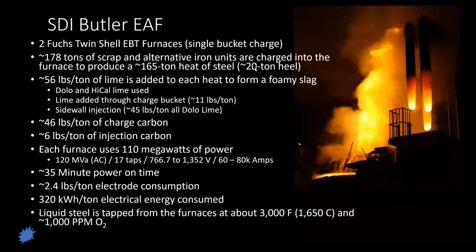With the twin shell, we aren't putting power on one of our shells for say 35-40 minutes. So if you have a really big heel in there, you have heat transfer that whole time, and you lose a bunch of energy that you have to heat back up later.